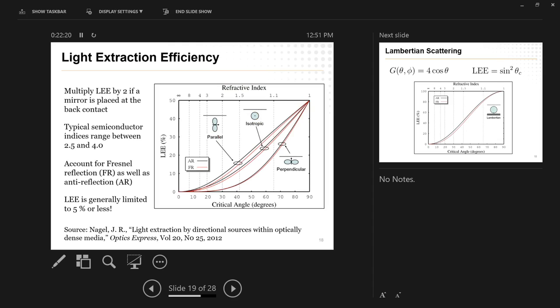And this is the curve that you get out of it. So this is a fun little intuition-building graph, because you see up here, you have the critical angle going from 0 to 90 degrees, and at the top, you have the refractive index that kind of corresponds to that. So obviously, if they're matched, if I'm emitting from air to air, there's no critical angle at all. It's 90 degrees, and my light extraction efficiency becomes 50%. Or, in principle, you can put a mirror at the back, and then all these numbers just multiply by 2. And then, of course, as the index of refraction grows up to infinity, you get a critical angle of 0, and nothing escapes at all. And then kind of these little transmissions, or transitions between the two. So you can see the middle case here was the isotropic, a nice simple case. And there was the parallel orientation, so it's beaming energy into the surface, and you see it's a little better. And the perpendicular case is awful, because all the energy is just being shot. It's sideways, and you get terrible extraction efficiency there.